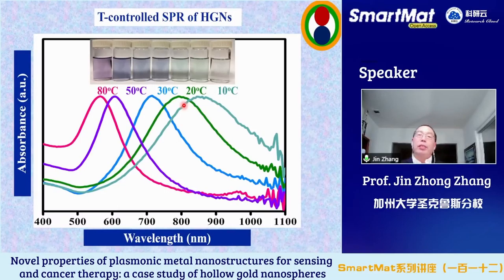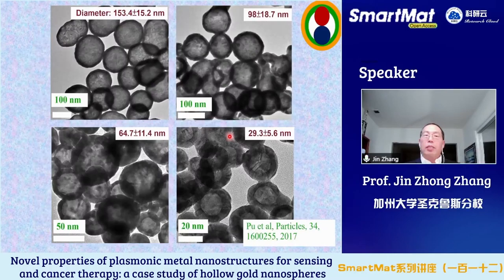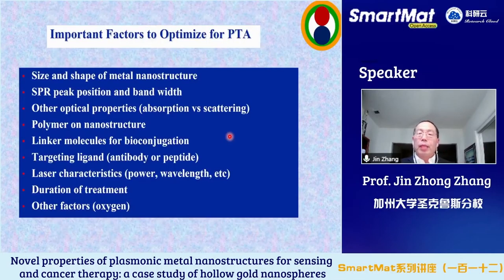We can also change temperature. This is done by Frank Song, an undergrad in my lab. He's now a grad student at UCLA. By changing temperature, keeping everything else the same, we can change the absorption. And this is the change in the size and the thickness of the HGN. Not as uniform as Sarah's, but the important point here is that now we can change the outer diameter from 25 nanometer to 150 nanometer, which is remarkable. I will try to wrap it up here.